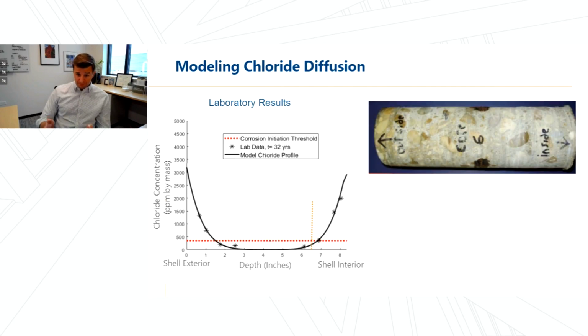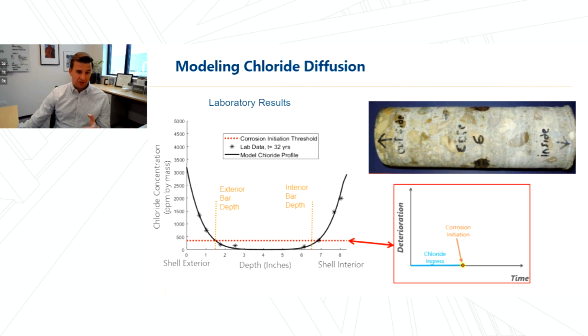For a similar cooling tower, we've taken a core and measured through analytical chemistry the chloride at various depths. When we look at this plot, you see the data points and then the black fit curve to that. At the shell exterior and at the shell interior, we have high concentrations of chlorides due to exposure on both faces, and those diffuse into the concrete, but towards the center of the shell, they're quite low. It's helpful to compare this to a corrosion initiation threshold. Recall, that's the point at which the concentration of ions has reached a level where the steel can depassivate and initiate corrosion. By evaluating the measured chloride concentration at the depth of the reinforcement and comparing it to this nominal chloride threshold, we know a lot about the structure now, and this does help inform what we know about the structure in the future.